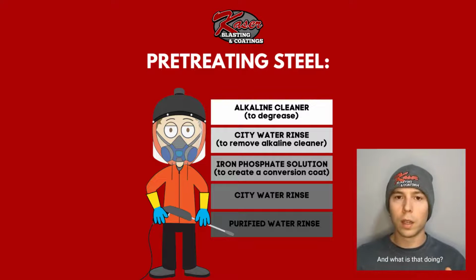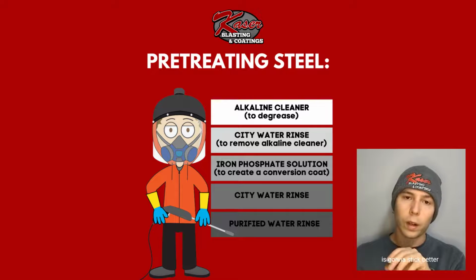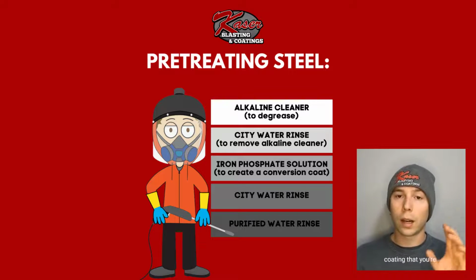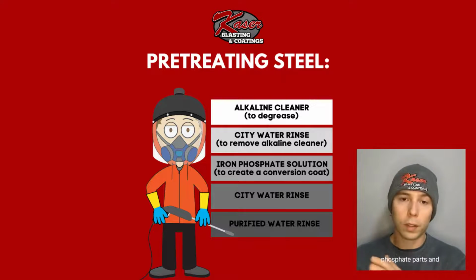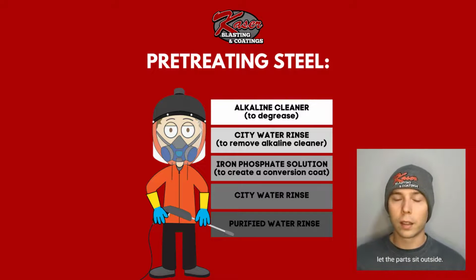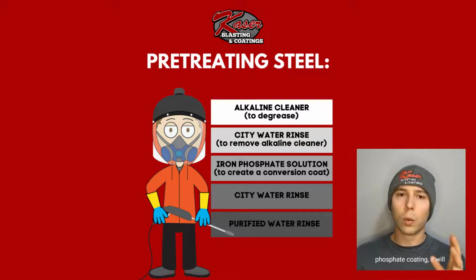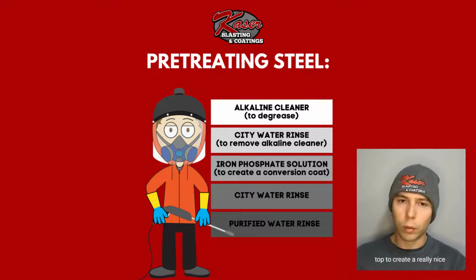And what is that doing? That's keeping the part from rusting a little bit, and it's also going to help with adhesion. So the powder coating is going to stick better to that iron phosphate coating that you're actually leaving behind on the part. It does help with rust prevention a little bit, but you can't just phosphate parts and create an iron phosphate coating and then just let the part sit outside. It's eventually going to rust. So the phosphate, when it creates an iron phosphate coating, will help with some corrosion protection for a while, but you really need to get the powder coating over top to create a really nice, good all-through coating from what you left behind with pre-treatment and then your powder that you put over the top.